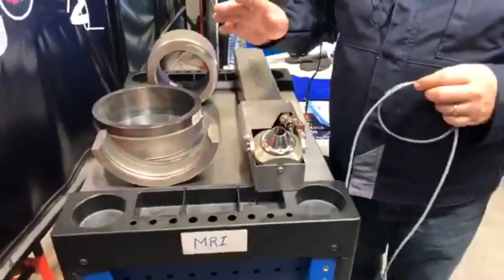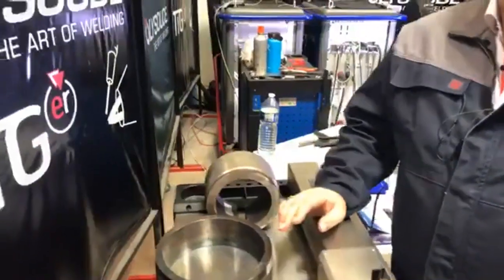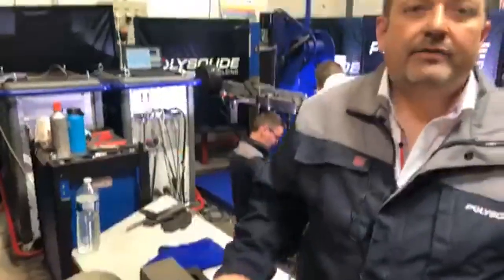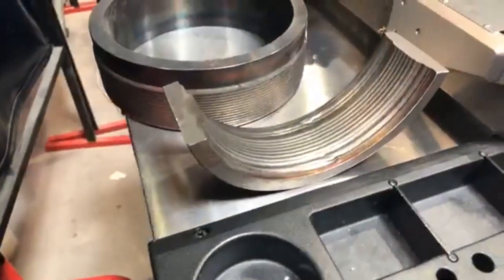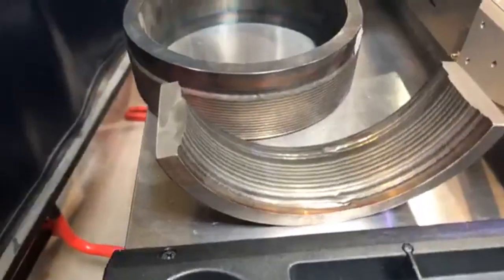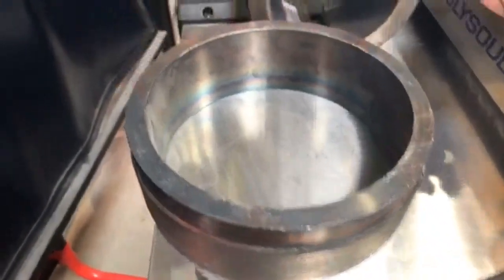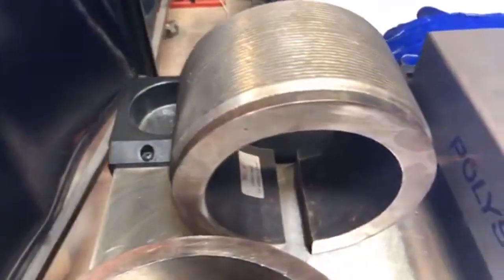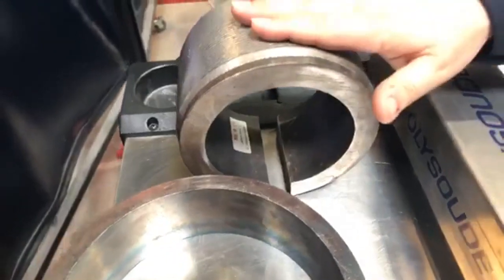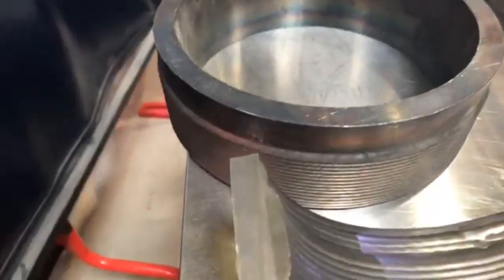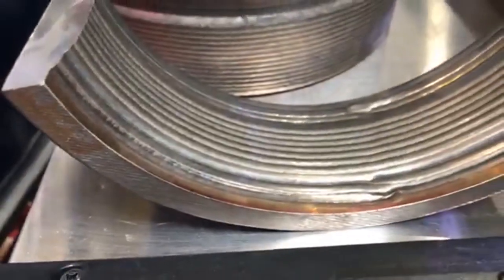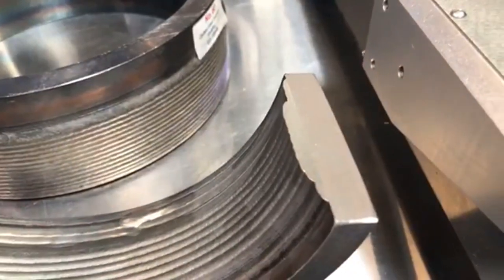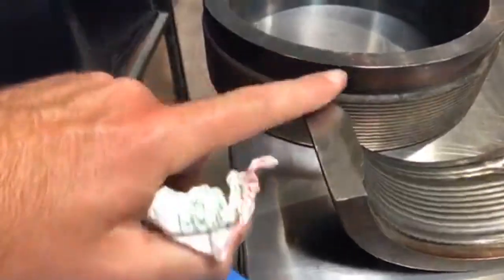So it's like Hervé mentioned. It's not only limited to flat surfaces, so we can weld in 1G or in 2G. We can weld on flanges, but also one of the preferred applications is the inside of pipes. So we start from 100 mm, and we can go up to 72 inches pipe cladding. We can also do cladding on the outside of the tube, and here you can see some of the test pieces that have been done, all using a carbon steel base and an Inconel 625 layer, 2 layers on top actually.